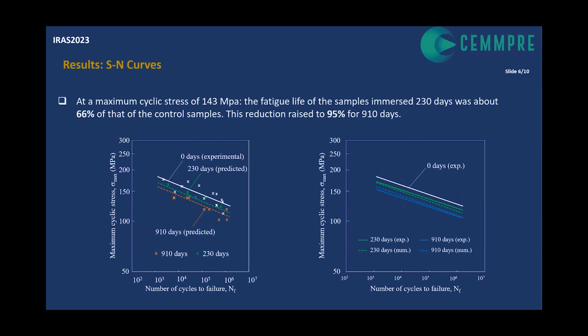In this graph on the left, the dashed lines represent the predicted results, and in the graph on the right, we have those same dashed lines, and we also have some solid lines which represent the mean curves obtained with linear regression from the experimental data. Overall, the numerical predictions were very satisfactory for either 230 days or 910 days of immersion. In the former case, the SN curve is slightly conservative, which is positive from an engineering point of view, while in the latter one, the numerical results were well balanced throughout the entire range.